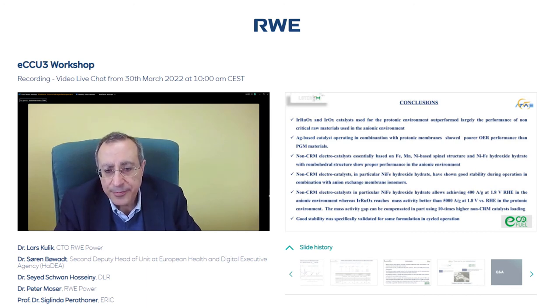Of course, we can have an enhanced reaction rate using these advanced catalyst formulations with 10 nanometer particle size and good dispersion. With this formulation, we can achieve 400 amperes per gram at 1.8 volts versus the reversible hydrogen electrode. This is the raw performance, not corrected for ohmic drop. That means this is appropriate to achieve high current density. Of course, it is not comparable to what we have in PEM electrolysis with iridium ruthenium oxide, but I think this is a good result. And of course, we can spend more energy on the cathode reaction, the CO2 reaction, in order to achieve practical current densities at a suitable voltage efficiency.